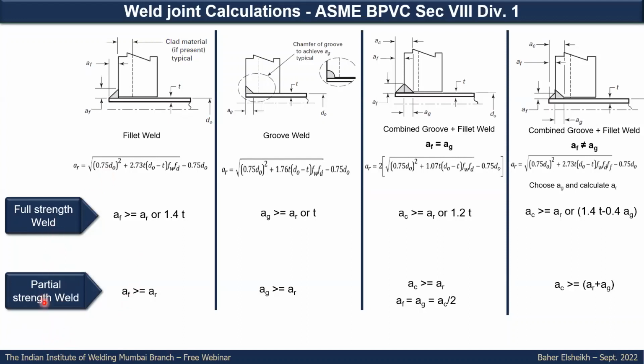But for the full strength and partial strength weld, there are some equations that need to be applied, where you can calculate the minimum dimension of the weld required. And if you can see here, the full strength weld is more stringent compared to the partial strength weld. Here it is whether the greater of AR calculated from the equation or 1.4t, while for the partial strength weld it should be greater only from AR.